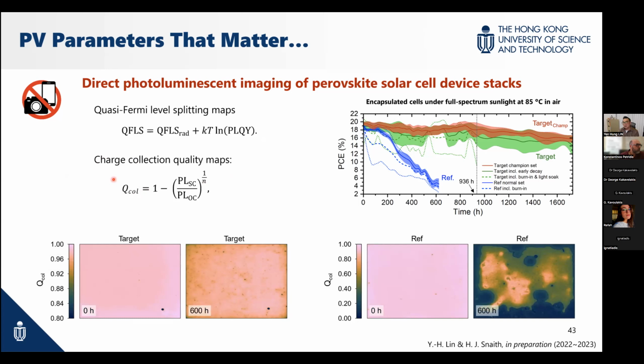Essentially, when we measure photoluminescence, we measure it under open circuit, which is the most straightforward way. But we also measure photoluminescence under short circuit. So we define how many charge carriers can be extracted, because for open circuit, we expect the film to be very luminescent since the charge carriers are accumulated within the film, and in open circuit we don't collect any charge carriers. But for short circuit, the film is supposed to be very dark. Then we did this kind of calculation, basically to examine how many charge carriers can be extracted out of the film.